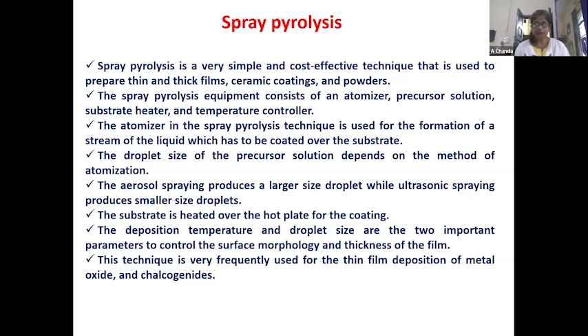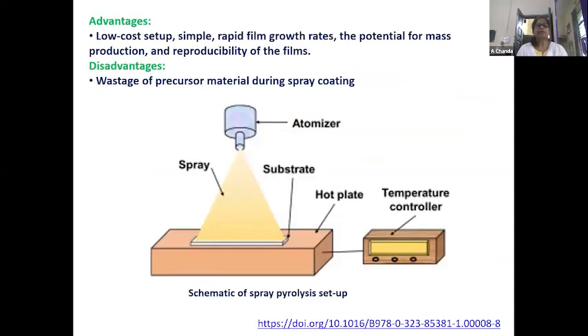In the deposition, the most important parameters are the deposition temperature and the droplet size. These two parameters control the surface morphology and thickness of the film. This technique is very frequently used for oxide and chalcogenide materials deposition. The advantages are a low cost setup, simple and rapid film growth rates, potential for mass production, and reproducibility of the films. But wastage of precursor material during spray coating is the main demerit of this technique.